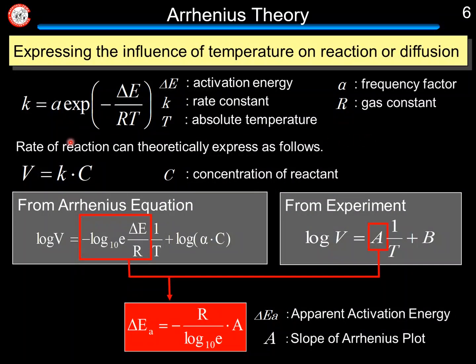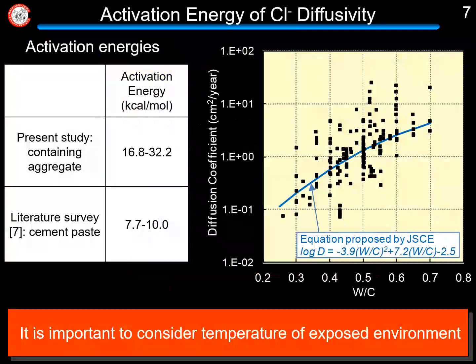Here, the Arrhenius equation can be expressed as shown here, and this equation can be translated as follows. Also, we can obtain the slope of the Arrhenius plot, so the activation energy can be calculated from this equation. This table shows the activation energy obtained by this study and literature survey.